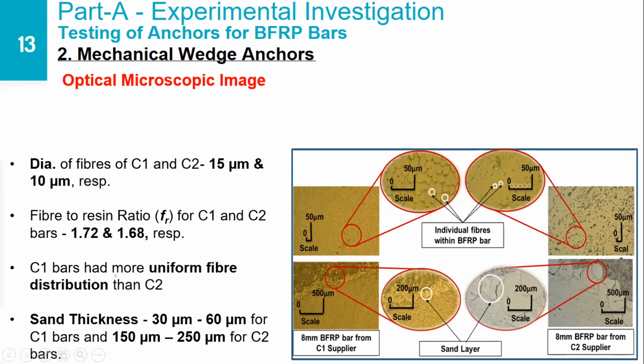However, it has been noticed that the bar supplied by the C1 supplier has a more uniform fiber distribution than the other bar. And also the sand that was coated on the surface was of size 30 micrometer to 60 micrometer on the bar supplied by the C1 supplier, and it was 150 micrometer to 250 micrometer on the bar supplied by the C2 supplier.